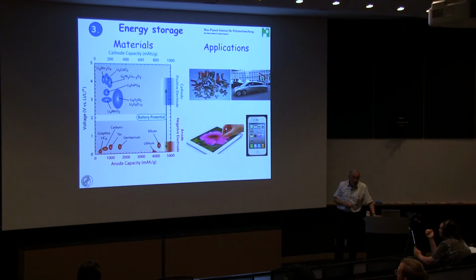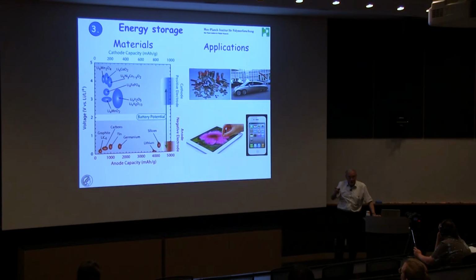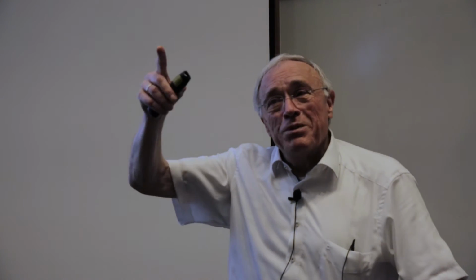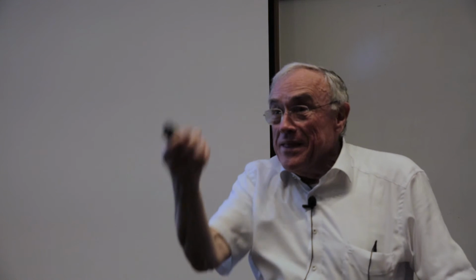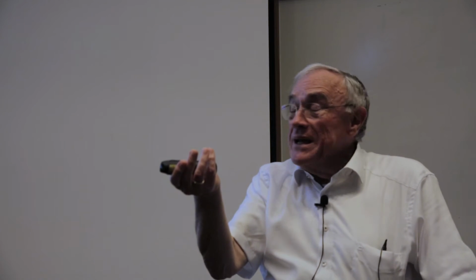The same holds here. When we talk about energy storage trouble, graphite, which is normally used in a lithium battery, has a poor, look at that, poor storage capacity. Inorganics are much better, but they have this problem, can you understand? When you put in ions and take them out, they are morphologically not stable. So what we did in our attempt at doing that, we took the best of two worlds.